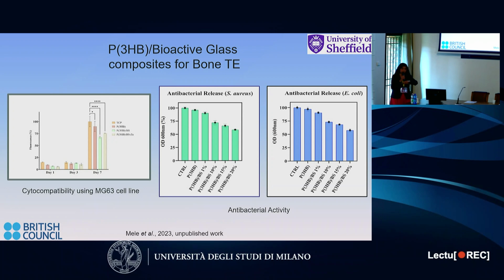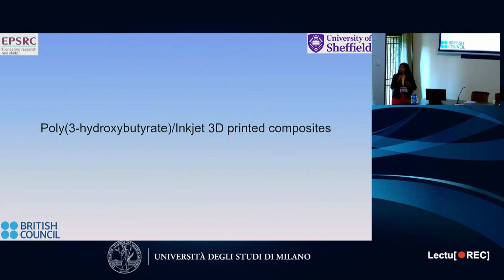Another very important property that I looked at was antibacterial property. We all know that many patients suffer from sepsis when they undergo these operations, especially the elderly and immune compromised. There's a lot of mortality because of sepsis. So if the construct itself can be antimicrobial, that will solve a lot of that problem. So we looked at antibacterial property, and we used Staph aureus and E. coli, and in both cases we observed excellent antibacterial activity. The zinc is the ion that causes that. So overall, we've created many composites.